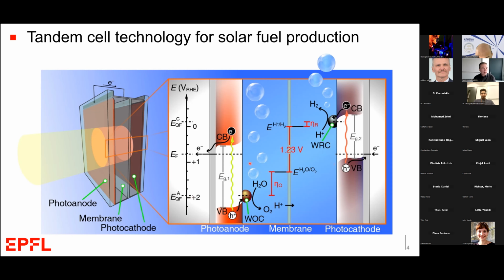And in the photoanode, photo-generated holes should travel to the semiconductor liquid junction and, at a catalytic site, oxidize water to oxygen. The electrons alternatively travel through an external circuit to the photocathode, where they're further excited by the semiconductor material, and photo-generated electrons travel to the second semiconductor liquid junction, reducing protons or reducing water into hydrogen. So to do this reaction, we need at least thermodynamically 1.23 volts of photopotential plus the overpotentials to drive the water oxidation and water reduction reactions. So our challenge is, of course, to find materials and systems that can perform this stably and at high efficiency.